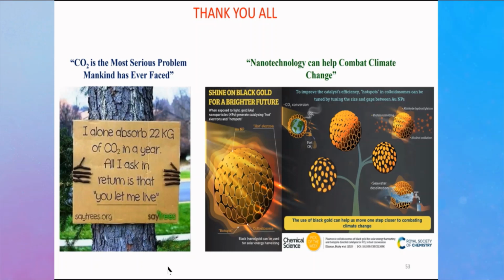It's 400 degrees Celsius thermal conversion. When I say 150 degrees Celsius on the gold surface, when the CO2 goes on the gold surface, it gets activated, it gets bent, and that helps reduce the activation energy and the temperature required for that particular reaction.